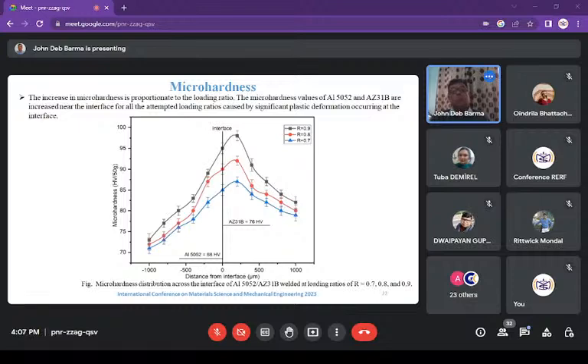Now let us talk about this micro hardness result. So as you can see, the disparity of this micro hardness across the interface of these composite plates at distinct loading ratios, that is 0.7, 0.8, and 0.9, are shown. And the increment in hardness, as you can see here, for 0.9, it is more. So it is proportionate to the loading ratio. That means more hardness for more loading ratios, as is consistent with the experimental work that is done by different researchers earlier.